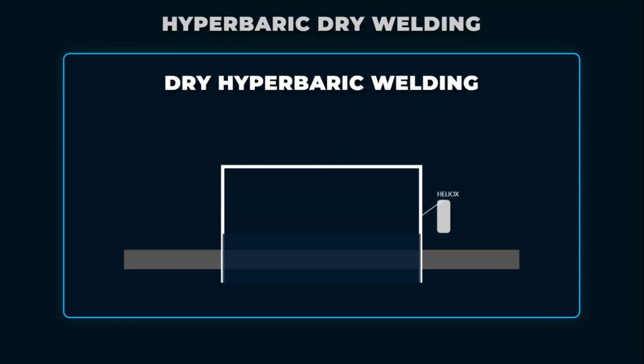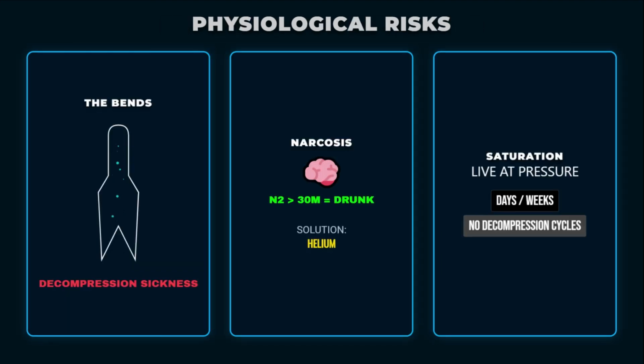For critical structural repairs requiring surface-level quality, hyperbaric welding is performed inside a dry habitat. This sealed chamber, pressurized to match the ambient water depth, displaces the water and allows the use of standard welding processes like gas tungsten arc welding or flux core arc welding. The habitat atmosphere is carefully controlled, typically using a helium and oxygen mixture known as Heliox to mitigate the physiological effects of nitrogen narcosis and reduce breathing resistance at depth. Even in a dry environment, the increased pressure affects the metal transfer mode and arc stability, necessitating precise calibration of wire feed speed and voltage settings.